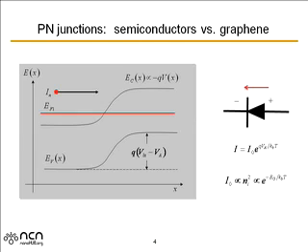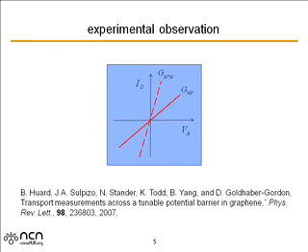But there are some really interesting effects that people are predicting will occur, and people are doing measurements on graphene p-n junctions that are also interesting. So one of the basic ideas is, and this is some really nice work that has been coming out of David Goldhaber-Gordon's group at Stanford. These are measurements that show if you make an N+, heavily doped N-type graphene junction with a moderately doped graphene junction, you'll get a linear conductance. Doesn't rectify, you don't expect it would rectify. If you do a graphene p-n junction, it doesn't really rectify. You get a linear conductance.